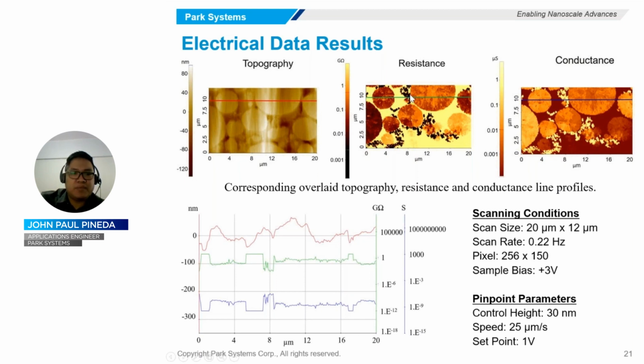The resistance image features brighter colored areas that represent higher surface resistivity, while areas with darker color represent areas that have a lower surface resistivity. So when comparing topography and resistance, one can easily observe that higher circular plateaus have lower resistance when compared to low-lying areas.